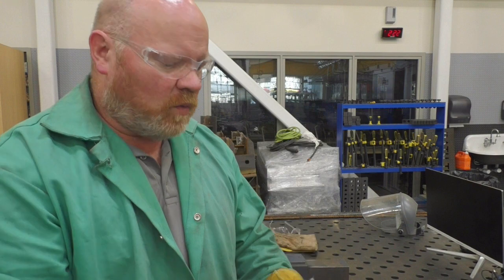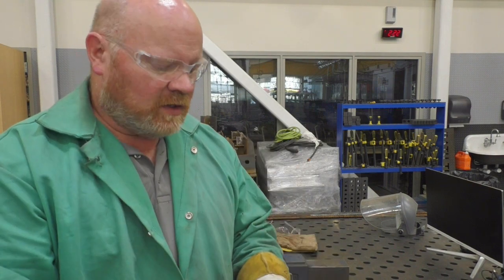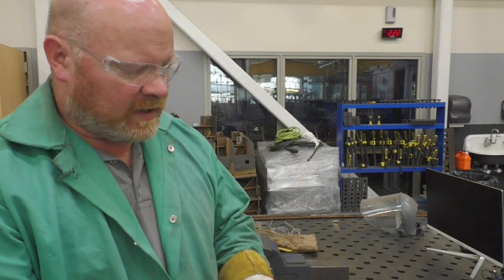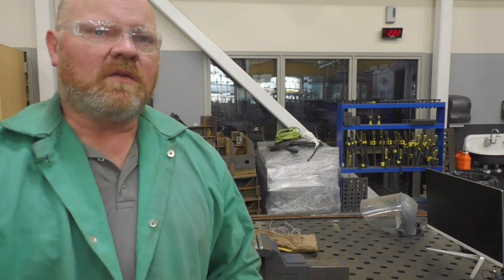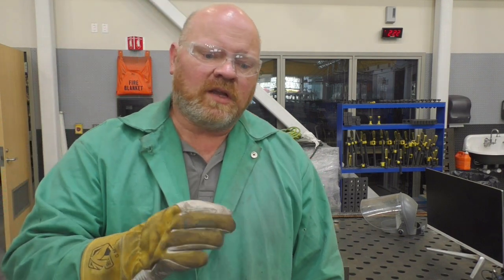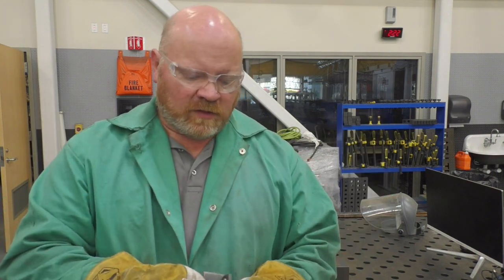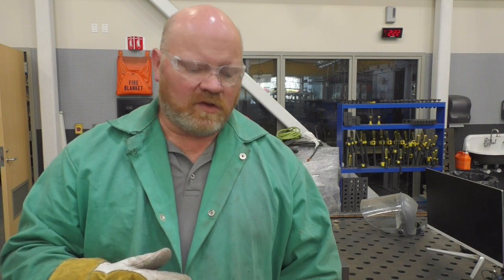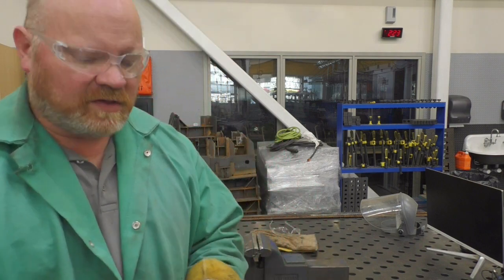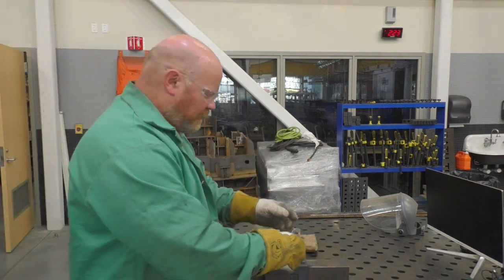Second one, here's your little 110 plug-in MIG welder, and I'm gonna test this out. I would particularly test your machine if you're running self-shielding flux core. You get one of those machines that welds without gas. That flux core wire will absorb moisture. You may find that even though it seems to weld and it looks like it's penetrating, your welds may be full of pinholes, okay? And that's gonna seriously affect the strength. So I'm gonna do the same thing right here.